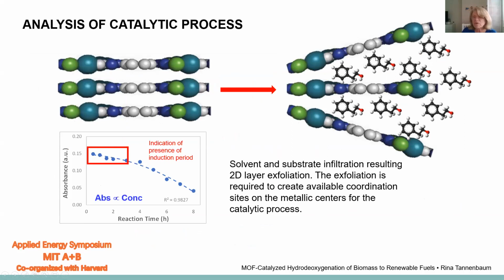it takes some time for the solvent molecules, this is the alcohol substrate molecules, to actually penetrate inside the layers, and really by the pressure of the solvent and the substrate molecules, they actually break the stacking interaction and exfoliate the layers, the 2D layers, and coordinate to the metallic center.